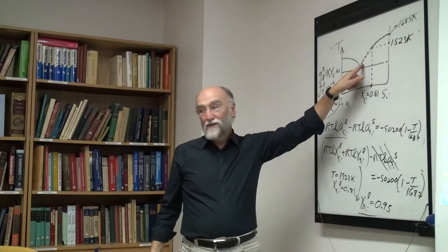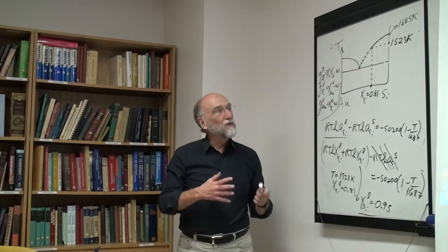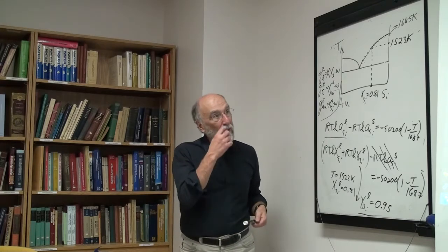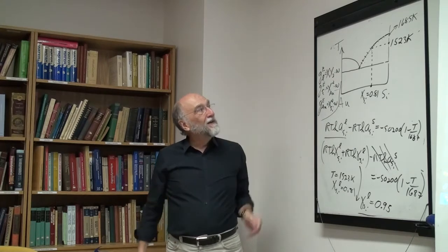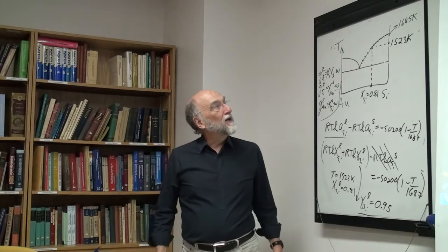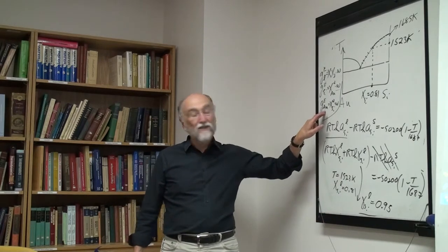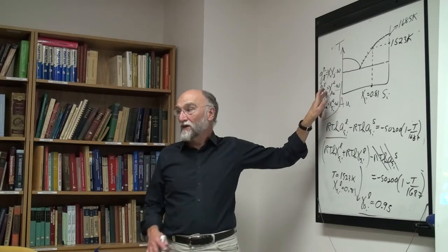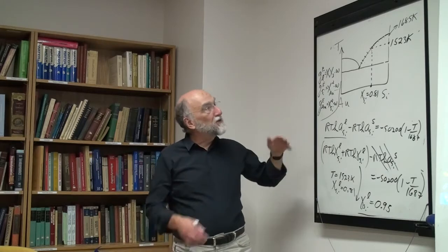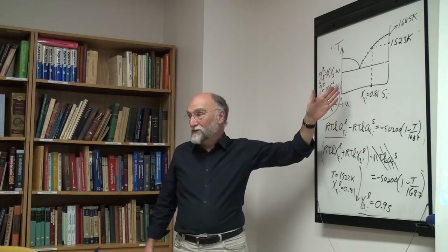Because all you've got is the GXS of silicon. It's your model that's gone back and given you GXS of gold, but there's no real reason to assume that that's going to be exactly right. Now we can talk about that more later. Yes, there is some reason, clearly, but it has to do with endpoints of integration and so on, but I'm introducing something I'll talk about next week. But you see that the actual information that the phase diagram is giving you is not the excess Gibbs energy of gold, it's giving you the excess Gibbs energy of silicon, period. You're not getting both, you're getting one. But when you optimize this thing, you can fool yourself into thinking you got the GXS of gold, but you really don't, and it has to do with endpoints and so on.